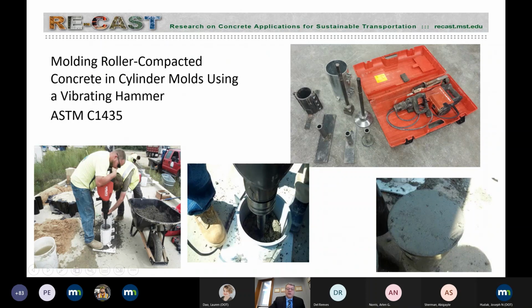The consolidation, if you haven't seen the consolidation of samples for RCC or CCP, is very intensive. So this is covered by ASTM C1435, using probably a vibrating hammer, applying pressure and then casting them in 3 layers and applying pressure until you get a sample. Each sample takes about 5 minutes to prepare. It's a long process and it's labor intensive.